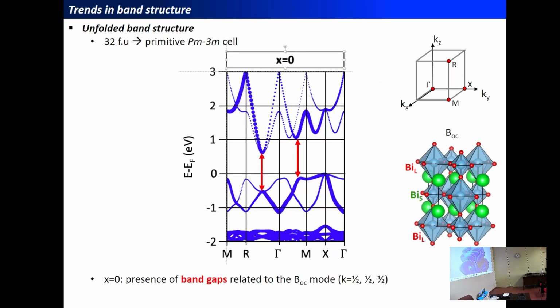So in these materials, we have a breathing distortion which is intimately related to the electronic structure, and so we can look at the effect of the breathing distortion on the band structure of the material. Firstly, we can start with the pristine material where there is no doping. As you can see, the unfolded band structure to the primitive perovskite cell is insulating, but you see that there are some gaps appearing here and there in the band structure.